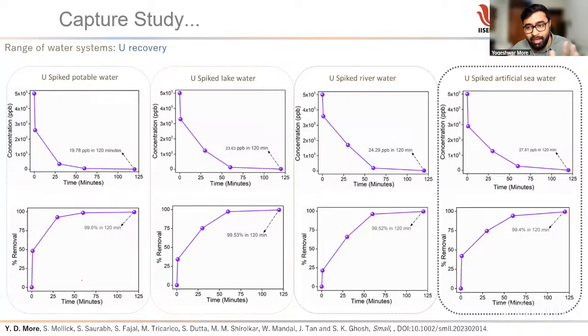Now you go to uranium spiked artificial seawater. Why artificial seawater? It has some 22 types of cations. It is modeled on whatever the seawater actually is; we prepared the same seawater in the laboratory in a very standardized manner, given the formulation. And then we tested our kinetics. So we were able to extract nearly 27.81 ppb in 120 minutes, that is nearly 99.4%.